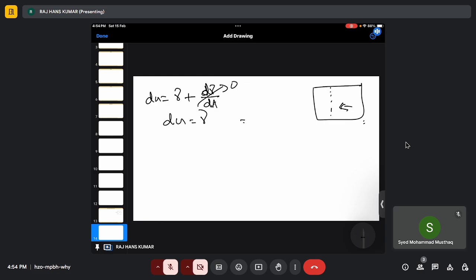Work done means, how do you represent the tension? The tension per unit length times the area will give me the surface energy. Right now, what is my T by L? T by L is my surface tension, right? So dG upon dA, right? So this area will get cancelled. So my surface tension will be equal to surface energy. So that's why in liquids, the surface tension will be equal to surface energy.